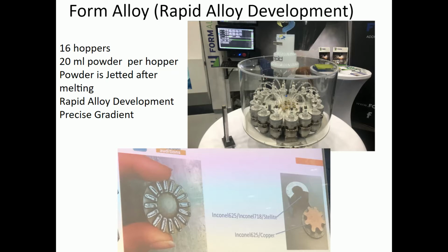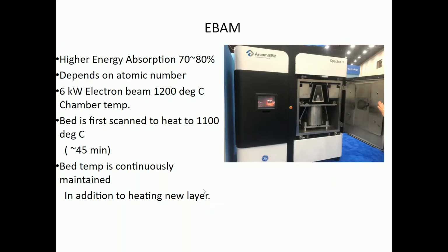EBAM, or electron beam additive manufacturing, is widely used in the aerospace industry. One interesting fact to note is that the bed of the machine is first scanned by the same electron beam and brought up to 1100 degrees Celsius, and this takes about 45 minutes. The build chamber is also maintained at 1200 degrees Celsius. A 6 kilowatt electron beam is used and the energy absorption is about 70 to 80% and is much higher than a laser sintering process. Shown here is an ARCAM electron beam melting system.